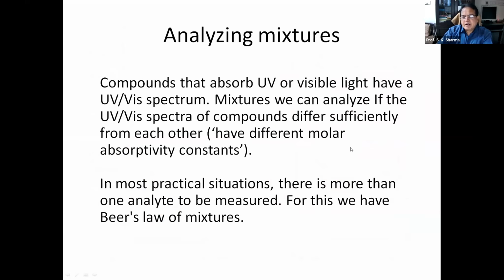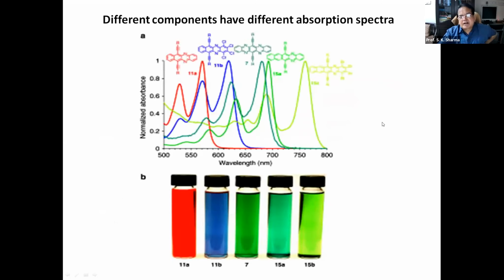Okay, and you can also analyze mixtures. Instead of one material in your solution, you can have more than one material, but they should have different molar absorptivity constants, and you can measure these two different materials. For example, here different colors of curves are shown to you. One particular red chemical has a red peak, and this blue one has a blue peak. But if they overlap completely with each other, then this technique may not work. But if they do not overlap, then you can determine the concentration of all components using this technique.